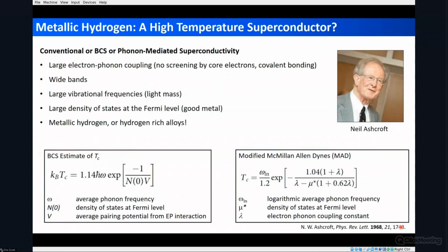And in the 1960s, Neil Ashcroft, pictured here, was the first to propose that if you were able to make metallic hydrogen, then it could potentially be a high temperature superconductor, a conventional superconductor, and Julia already talked about that. It would have a large electron-phonon coupling because there would be no screening. There are no core electrons to screen the electron-phonon interaction, and the covalent bonding would lead to this large electron-phonon coupling contribution.